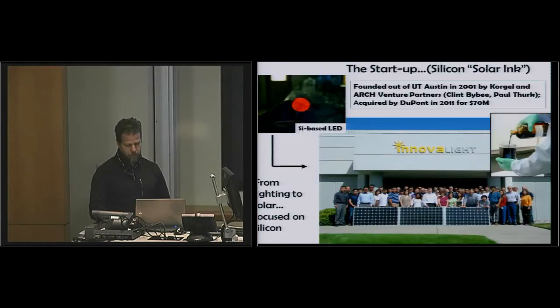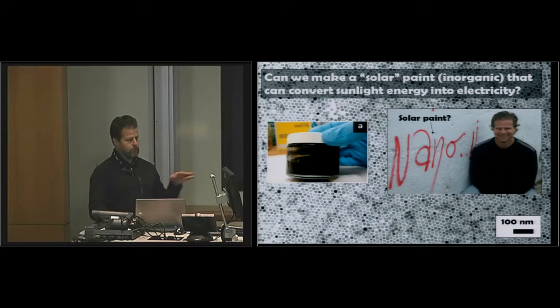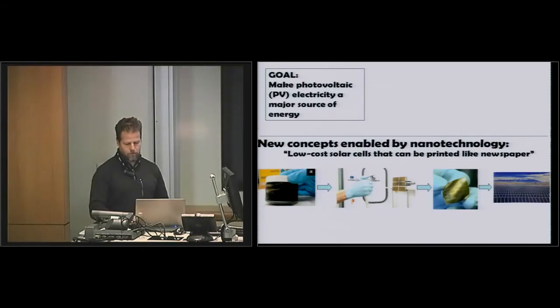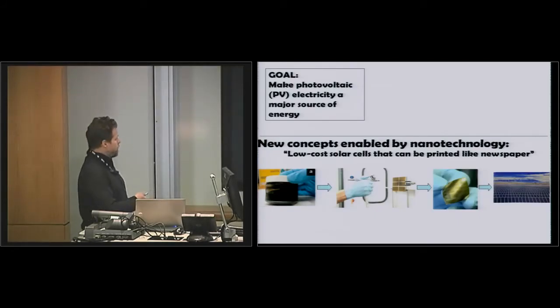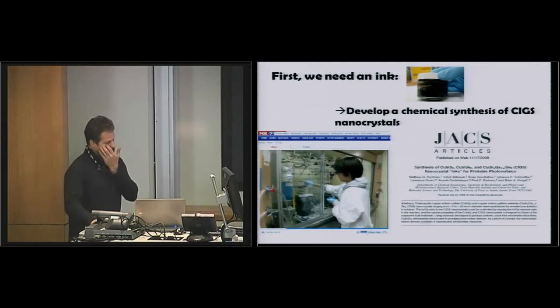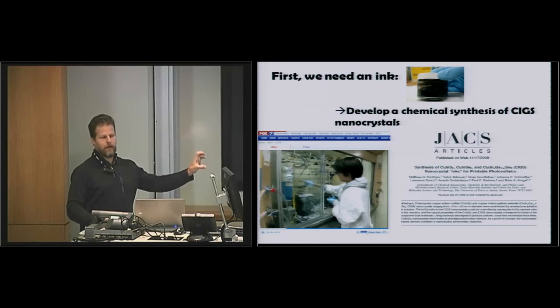And so that's kind of where we started. It was a really interesting synthetic challenge, really interesting material that nobody had made in terms of nanocrystal solar cells up to that point. And so that's what we started to do. And the idea was to make an ink that you could spray paint onto a surface and make solar cells. And so after a couple of years, we figured out how to do it. It actually turns out that this class of materials, these chalcopyrite compounds of copper indium selenide, copper indium gallium selenide, turn out to be really stable. And so you literally can just combine four elements in a flask, heat it up, and you get the chalcopyrite compound. Under certain situations, it gets a little more complicated than that, but it's really actually pretty straightforward.